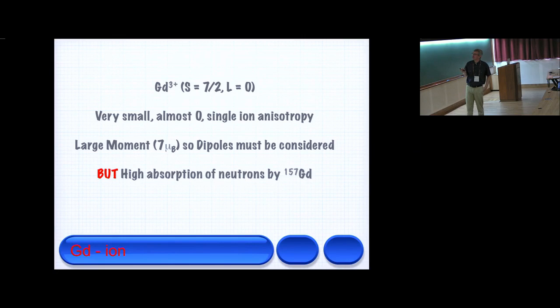Because of the absorption, we have to buy these expensive compounds where they've removed the absorbing isotope. It does have a large moment, which is a saving grace, so the scattering power is huge. So even with the small samples, we can get some data, as I'll show. If we were doing this with copper, with a spin half, we would be completely lost at 50 milligrams. It gets really hard.